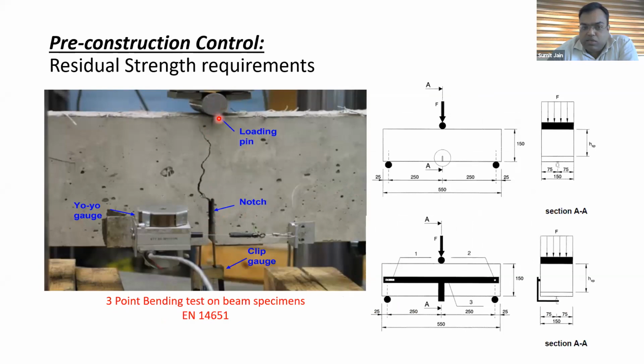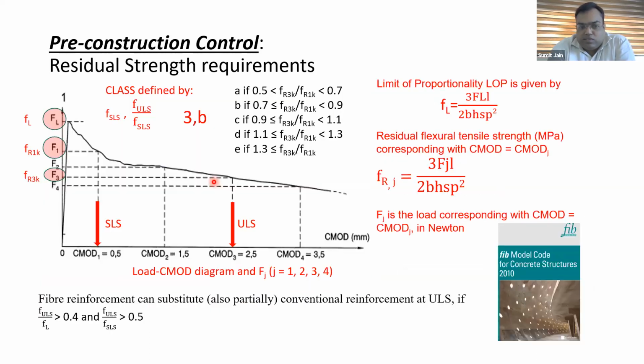So you can see a loading pin at the top. This loads the specimen, and the crack generates and travels up to the loading point. And this distance or gap between the notches starts to open up. The opening is measured versus the load which is being applied. Now this is the graph plot which is coming from the 3-point bending test.